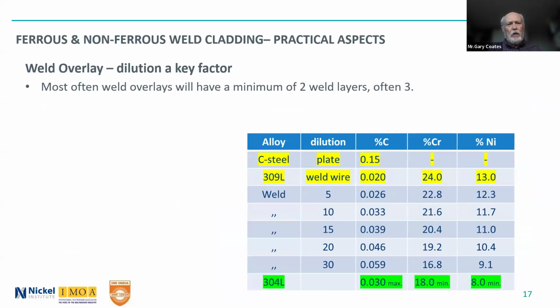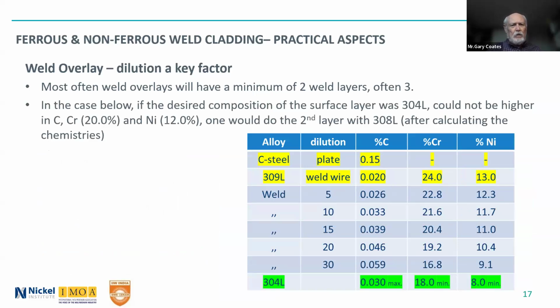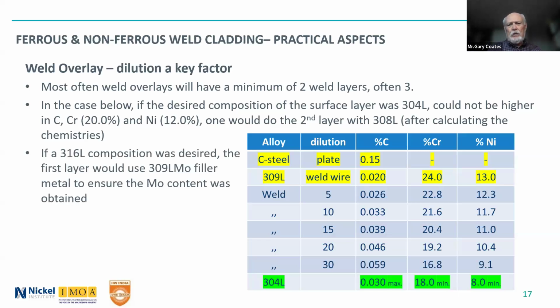But most often our weld overlays will have a minimum of 2 weld layers and often 3. So in the case below, if you really wanted 304L on the surface layer and you didn't want the carbon higher than the 0.030 max and you wanted the chrome nickel to be in spec, you would do a second layer with 308L after calculating the chemistries out, depending on the dilution of the first layer. If you wanted 316L, you would actually start with a 309L Mo filler metal because 316L has 2.0% minimum molybdenum. So you've got to make sure that you get the higher molybdenum content in that first layer, the transition layer.